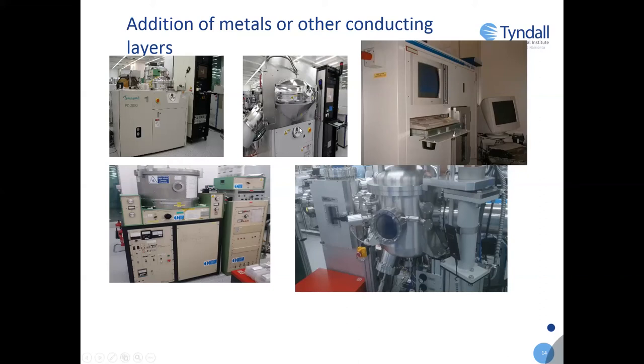We also then use evaporators. We spoke about E-beam evaporation of dielectrics. Similarly, you can do E-beam evaporation of metals. We have a number of systems. We have these two here in the 3-5 area. This is new. It's about 2 years old and quite eye-catching when you pass by. The metal evaporation is, I suppose, a bit like the E-beam evaporation for dielectric coating. You can pretty much evaporate any metal. So we would evaporate gold, platinum, silver, chrome, palladium, and combinations of the same. We've developed a process for gold tin evaporation, so that can be used for the eutectic, and you can use it for reflowing, solder reflow. So there's a variety of different methods of depositing metals or other conducting layers.